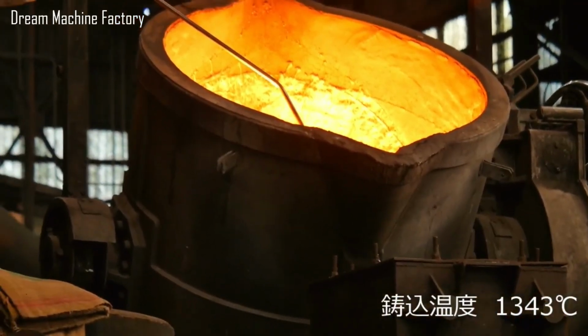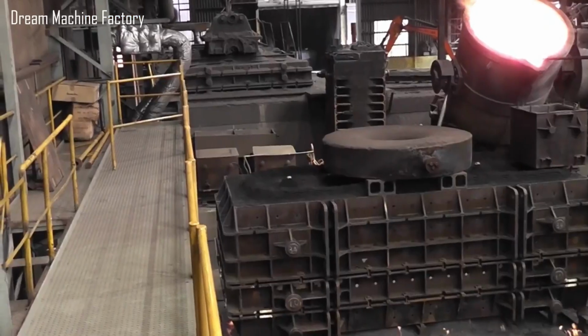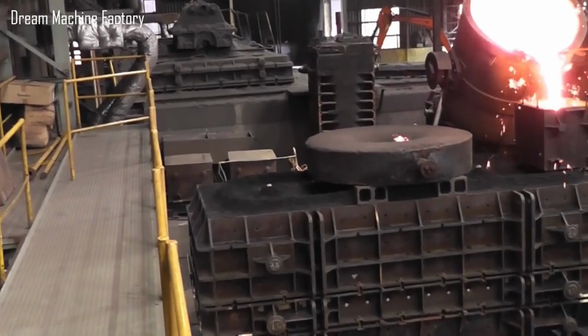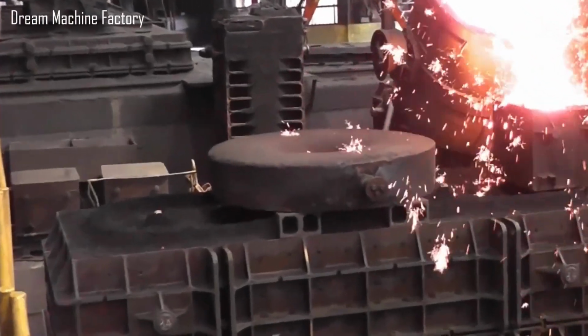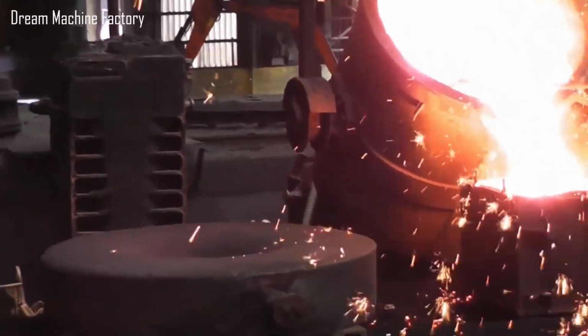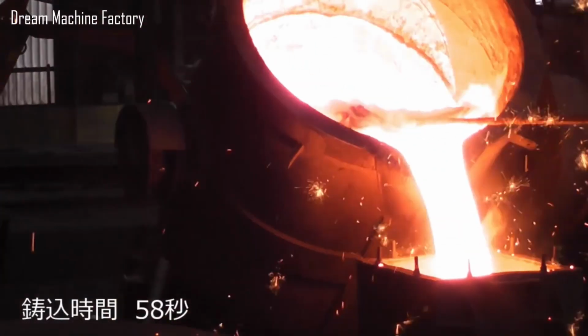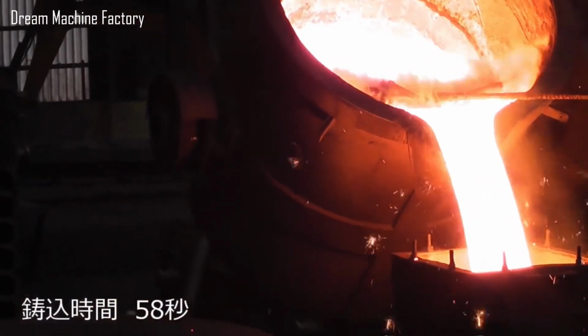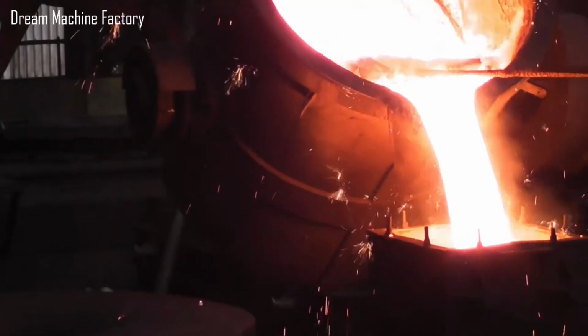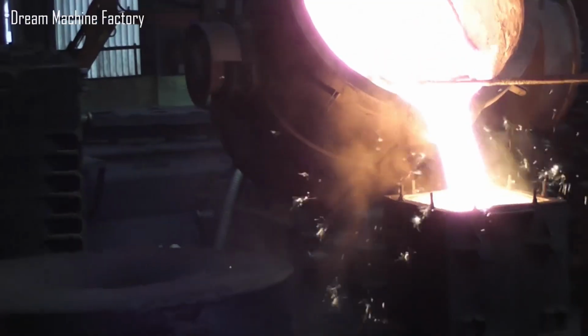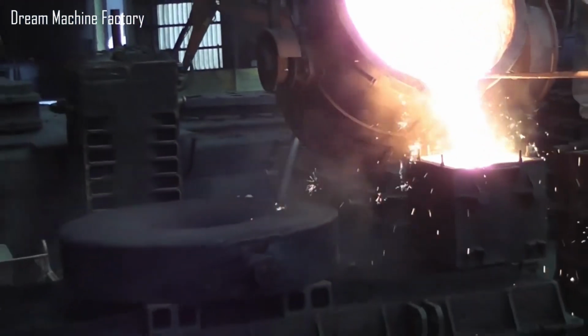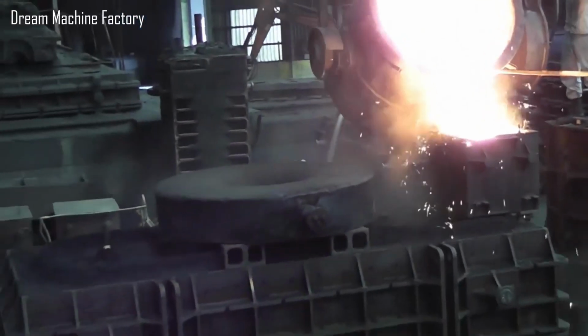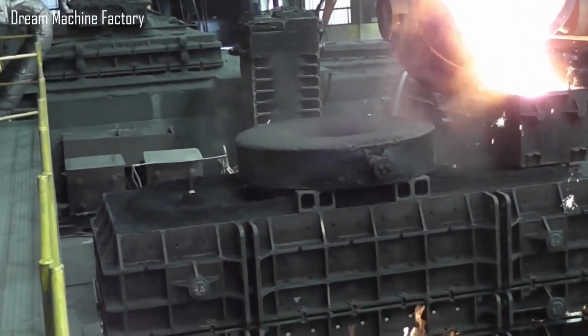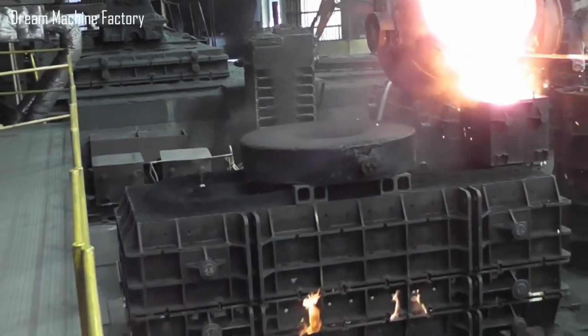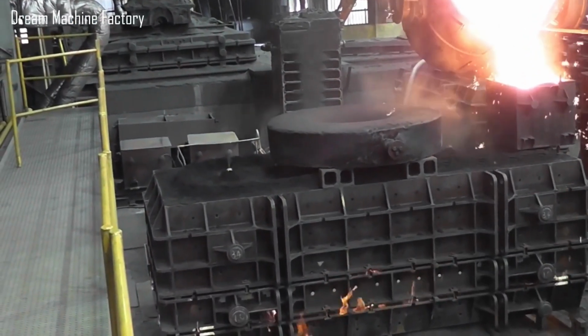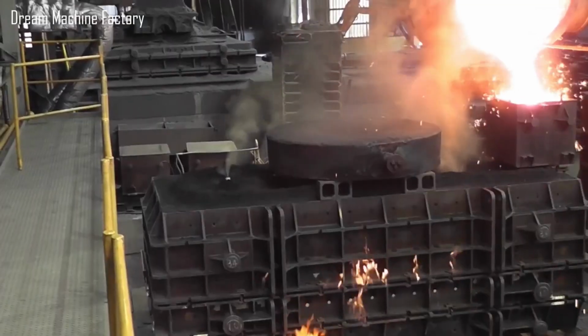At the same time, excessive superheating is avoided to minimize oxidation and gas absorption. The operation is carefully timed with a pouring duration of 58 seconds, which is optimized to achieve a smooth, continuous flow of molten metal into the cavity. A steady pour rate helps prevent turbulence, which can introduce air entrapment, slag inclusions, or erosion of the mold surface. Together, controlled temperature and timing guarantee uniform solidification, reducing defects and ensuring high-quality castings.